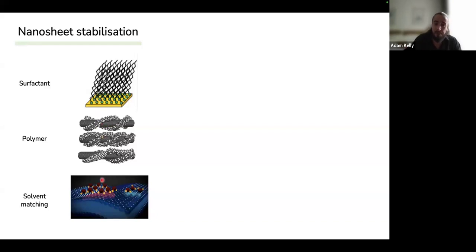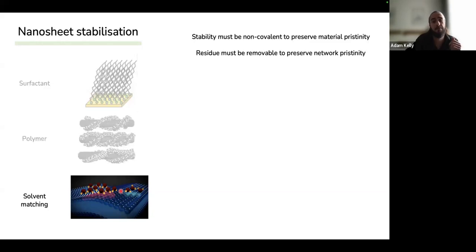So you take the surface energy of your solvent and you try to take a solvent with a surface energy as close as possible to the surface energy of your material. And what this means is that there is no energetic reduction when the material comes together. It's happy to stay in solvent as it is reaggregating. Now, this is probably the best way to do it for trying to make devices because the stability that you provide must be non-covalent to preserve the pristinity of the material, and any residue must be removable because once it's printed into a network, we want to make sure that the only thing in the network is our active material.